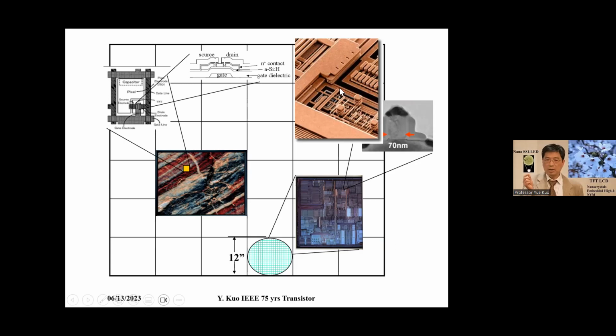So then the product can be working. For display, the same. Each pixel transistor, simple transistor, we have to connect with metal lines. The difference from the interconnect line here, in the IC, for example, state of the art is copper. And because the chip size is about an inch by half an inch, roughly, the interconnect copper had to be stacked up in 11, 12, or even up to 15 layers. The copper interconnect is multi-layer, and the smallest copper line is 0.5 micron, even less.